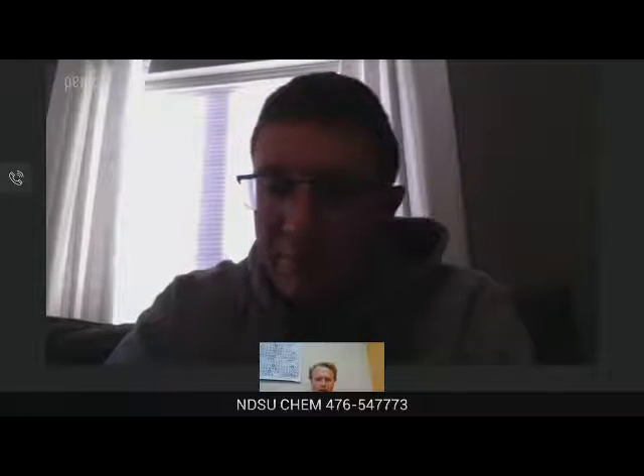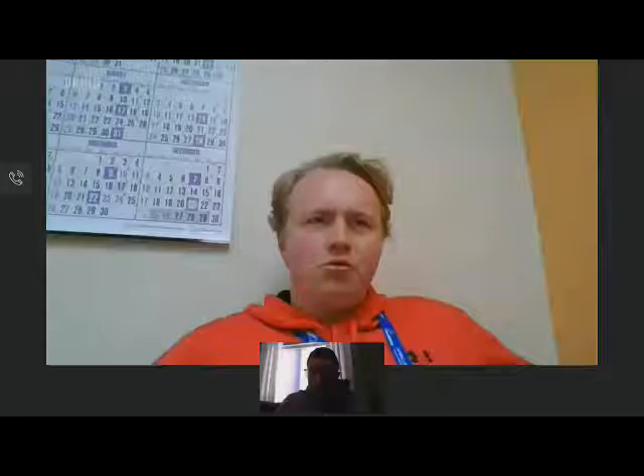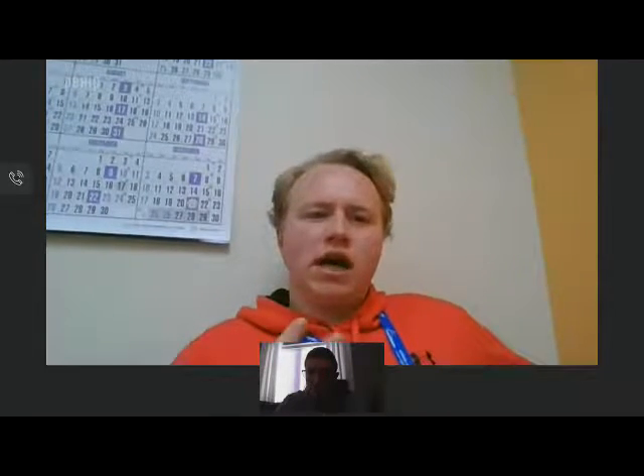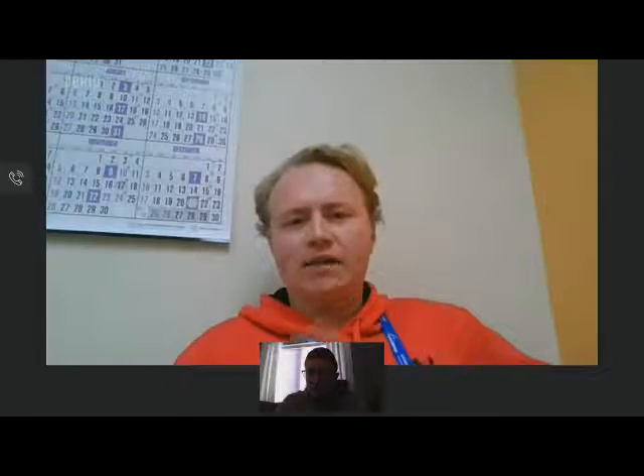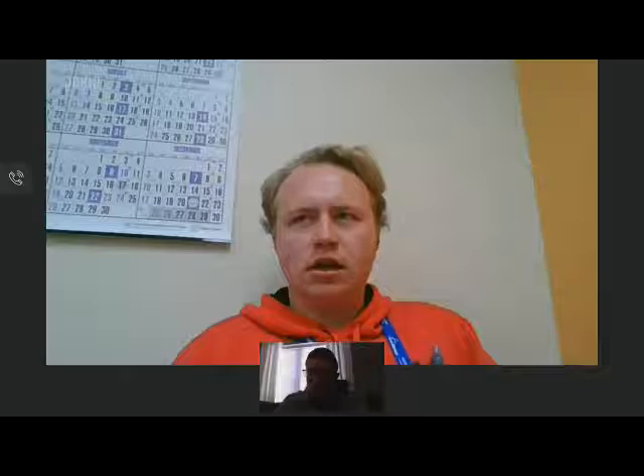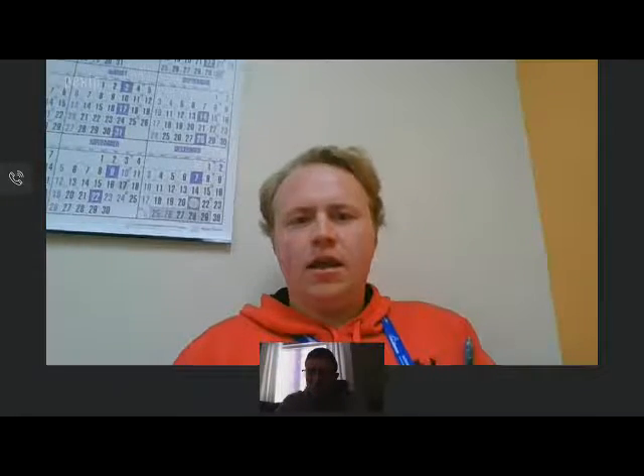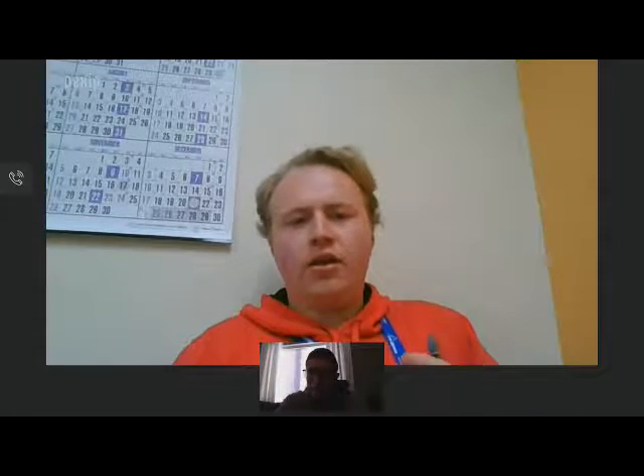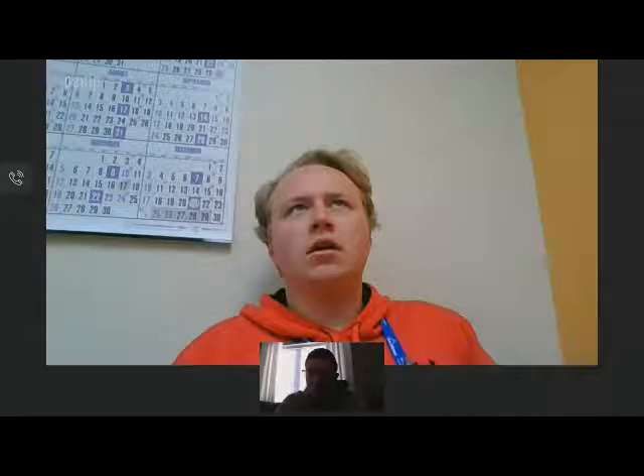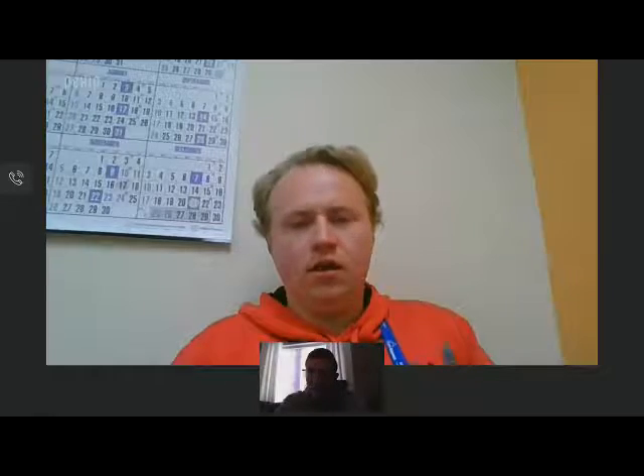Okay, so kind of basing off what we were just talking about. Levi, you're just looking at how when you change the chalcogenides, that's going to change the phonon modes more or less. Yeah. So how does the ratio of core to shell, like radius, impact non-radiative rates? So we didn't look at that because there's only 3 atomic layers that you can think about going from the center of mass out. And the first layer only has, I think, 8 atoms in it. And then the next layer has 8 again. And then the last, it has 8, then 16, I think, and then 52.